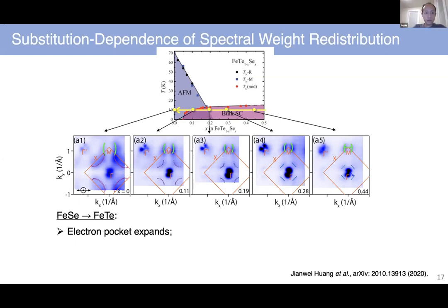Gabby, I think there is a practical concern from the photoemission experiment point of view: it's far from obvious you can get an accurate Luttinger volume counting. On the one hand, there are so many bands in pnictides that it's very hard to precisely determine kF. On the other hand, there is a three-dimensional Fermi surface, so you cannot just count the area on the map. I know on lithium iron arsenide we did that job. So I don't see any reason why it cannot be done here. It's just that the error bar has to be convincing.